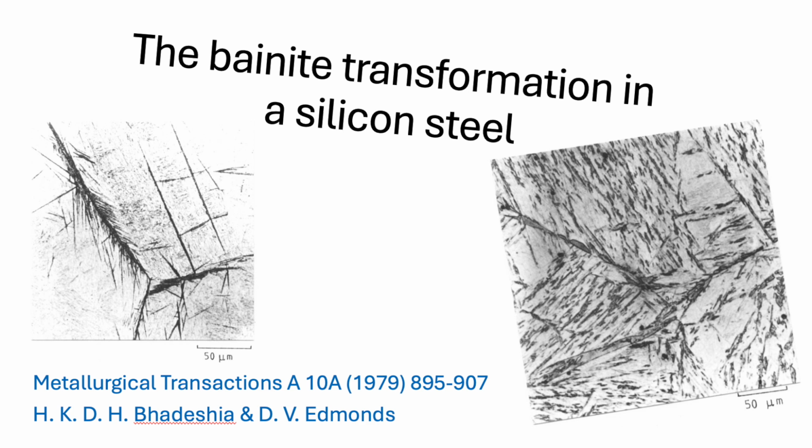Precisely. The parent material isn't just passively sitting there while atoms diffuse. It's physically straining, shearing to make room. That physical accommodation is a dead giveaway for a displacive, shear-based transformation mechanism. That makes a lot of sense. The formation itself involves mechanical deformation. Okay, so that's upper bainite. What happened when they tempered it?